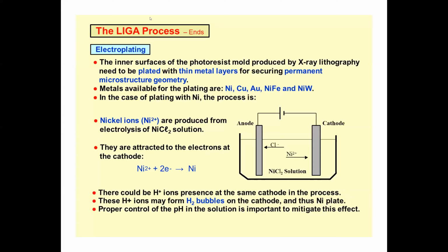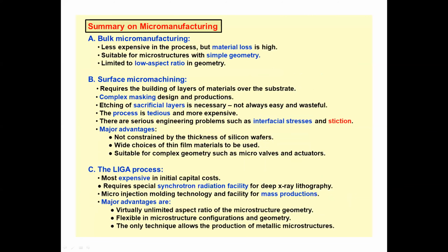So the summary of micromachining: bulk micromachining is the least expensive for microstructures with a simple geometry, but it is limited to low aspect ratio. For surface micromachining, you need deposition techniques for the structural layers, and you need multiple layers of lithography. Etching of sacrificial layers is very complex, where stiction, warping and collapse happen. So you should be very careful, and the process is tedious and expensive, and interfacial stress and stiction may happen. That is the issue with surface micromachining.